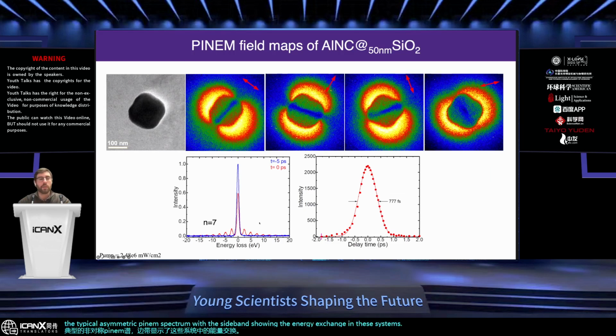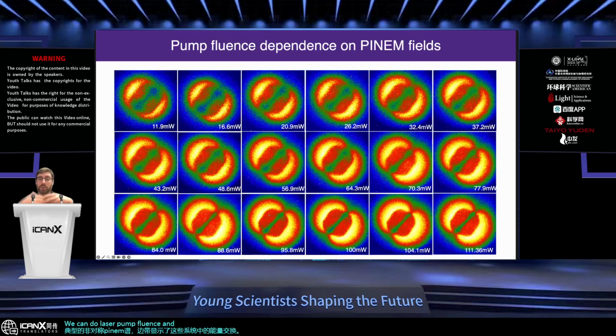We can do laser pump fluence, and we see that as we increase the energy, we get stronger field enhancements overall in these systems. And this, again, gives us some insight into how metal nanoparticles, particularly plasmonic metal nanoparticles, are behaving both in terms of field strength and intensity overall.